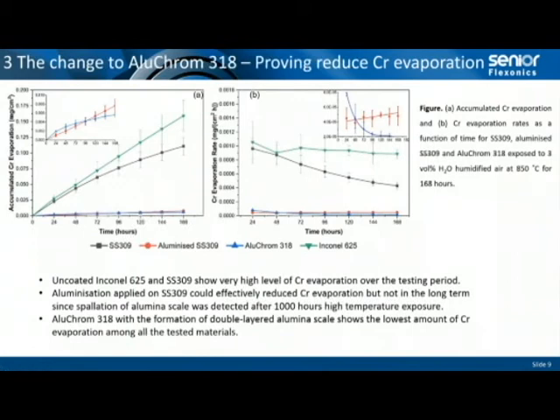Okay. Hi guys. My name is Kun Zhang, and as Charlie said, I'm a PhD student from University of Birmingham. And I'm responsible for the work package 4 of HEATSTACK project, which is material testing and analysis. So during the early stage of HEATSTACK project, the main task of work package 4 is to evaluate the chromium evaporation of 4 different high temperature alloys used for cathode air heater. So the alloys we tested are Inconel 625, stainless steel 309, aluminized 309, and AluChrom 318. So after the experimental evaluation, we selected the best material with the lowest chromium evaporation for developing cathode air heater.